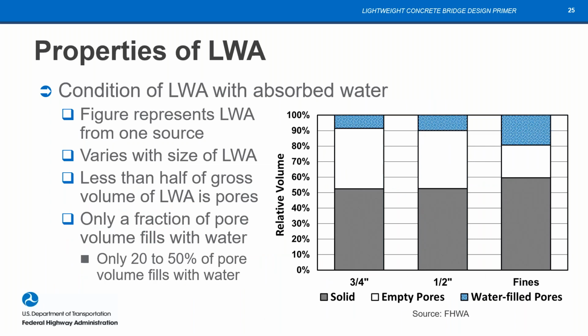This is a graphic that illustrates the condition of three aggregate gradations. This is theoretical, where you're taking a look at what's the solid portion of an aggregate, the pores, and then what of those pores can be filled with water when you reach that absorption that you might have seen in the preceding slide. So the absorption varies, but still, even though you have absorption that is essentially stabilized at this level, there are pores that are inside the aggregate that are not filled.